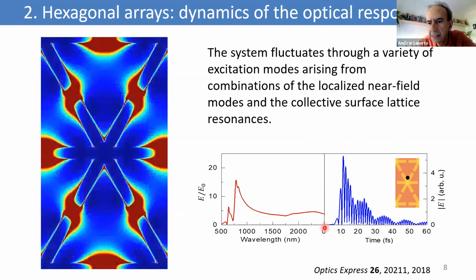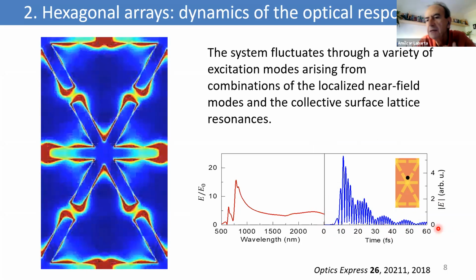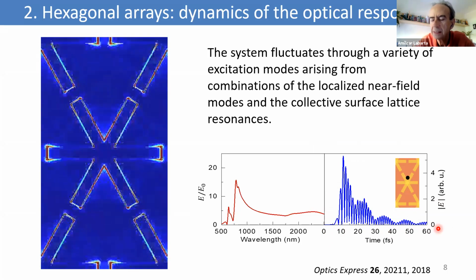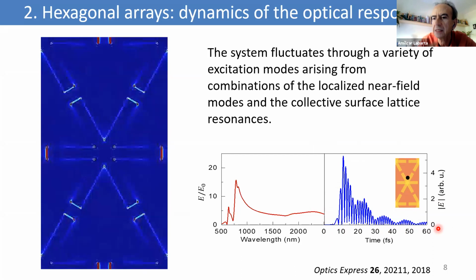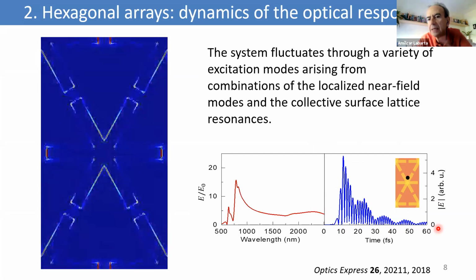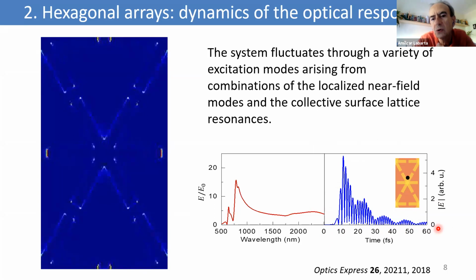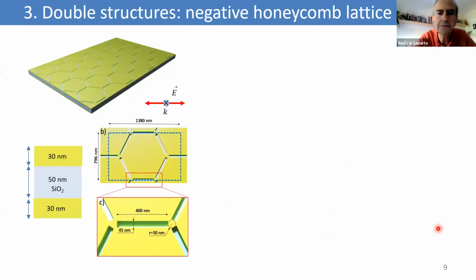There is a kind of modulation between two characteristic times, and what is more remarkable is the fact that the time decay is significantly longer than the duration of the excitation pulse. It's at least one order of magnitude longer. So these kinds of systems show at least one of the properties that you can find in geometrically frustrated magnetic systems, which is this long duration of the relaxation. I am going to move to another two examples.